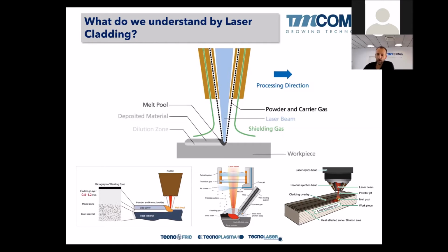Okay, so at the end we have a laser beam which is focused by some optics. And here in blue shape, we can see the laser beam that has been focused on the surface. With laser cladding, we concentrate all the power of the laser on the surface. We are not interested in cutting or deep welding, where in these technologies we have more penetration. We keep the penetration in the surface. So as long as we are in the surface, the dilution will be quite low.